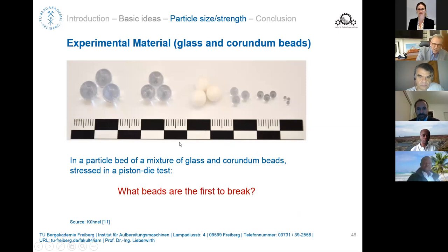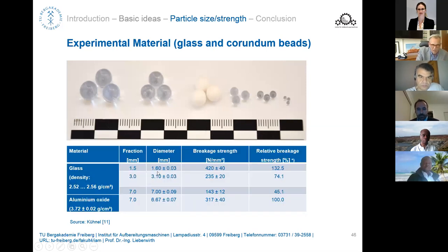With a piston die test, you see the variety of glass beads. We investigated the material quite extensively: 1.5 millimeter glass beads, 3 millimeter glass beads, and 7 millimeter glass beads. We ended up with the breakage strength of the material and the relative breakage strength here, which was the percentage of particles broken at a certain load.